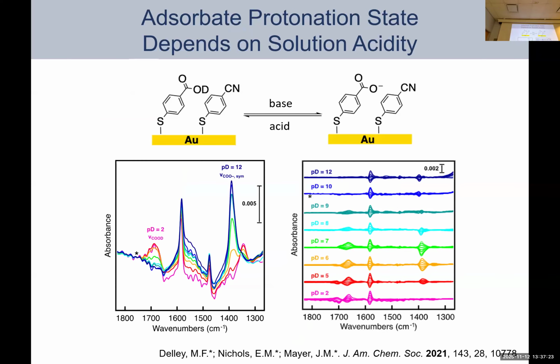Okay, so let me just orient you to what we're looking at. So we have these mixed self-assembled monolayers, and first things first, we're just going to look at their SEIRAS spectra, which is what this is, as a function of PD, or PD because it's in deuterated water. Okay, so in pink, this is the most acidic, PD of 2. And you can see a large sort of broad feature here around 1700. You see these really sharp features here. These are ring breathing modes in the sort of 1500 to 1600 wave number range. And then there's nothing present here right around 1400.